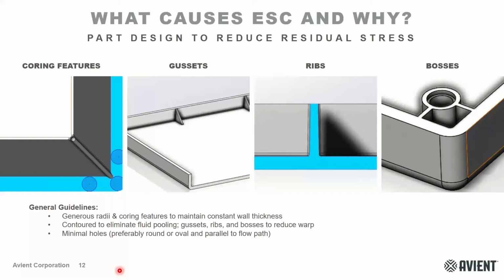A few other things such as gussets and ribs, as well as bosses to reinforce edges. These things can help to reduce warpage in a part. They have to be strategically placed. It's not simply by adding them will it ultimately eliminate your issues of warpage, but in a strategically placed manner using the appropriate conditions, these can prevent warp and eliminate fluid pooling. So that's important because if a part warps and creates a depression and it's being routinely sanitized and the fluid's allowed to pool, that can definitely lead to environmental stress cracking.